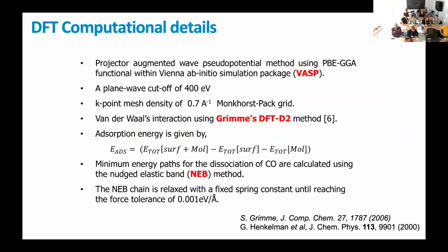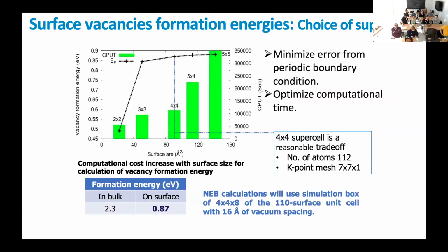These are just the computational details. So just to give you an idea, if you remember, when we were talking about the first case of the carbon decomposition on the iron surface, we face a challenge that many people in DFT calculations face when they are dealing with surfaces. When you build your slab, you make sure that your slab has sufficient thickness to be able to converge, okay?